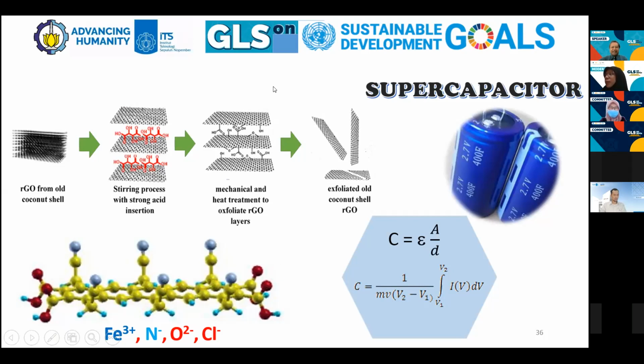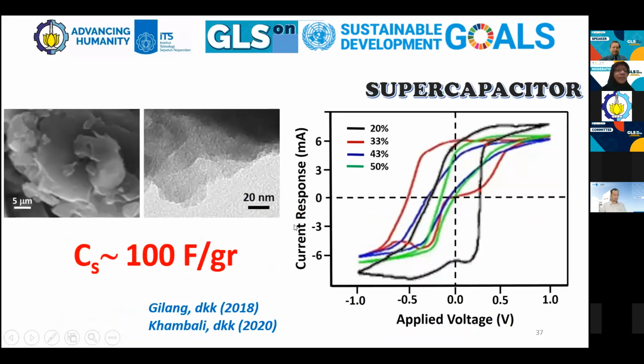So if we can increase the surface area, this one, and also the dielectric constant, this one, you may expect that you will have high specific capacitance. And this is the sample morphology of the resulting exfoliation. And from the IV curve measurement like this, the capacitance can be estimated, and the specific value of this material is around 100 farad per gram. This capacitance can still be enlarged by further exfoliation and substituting any other cation or anion on the graphenic sheet.